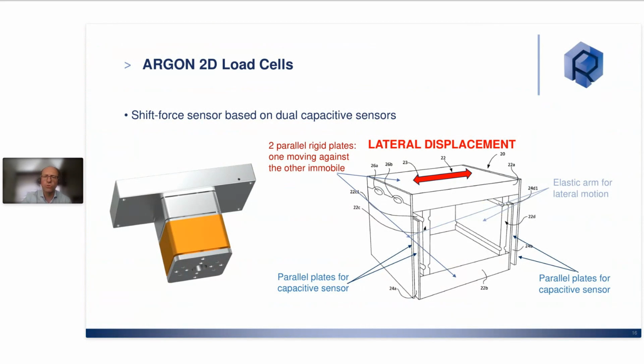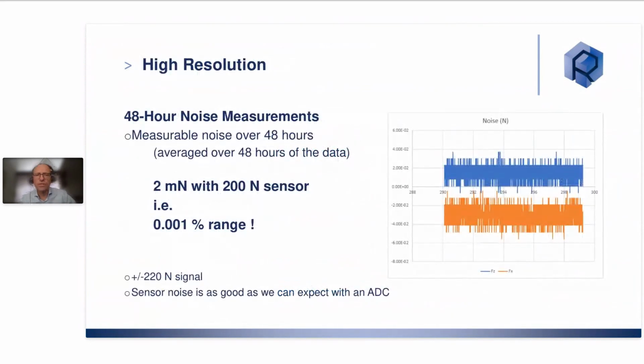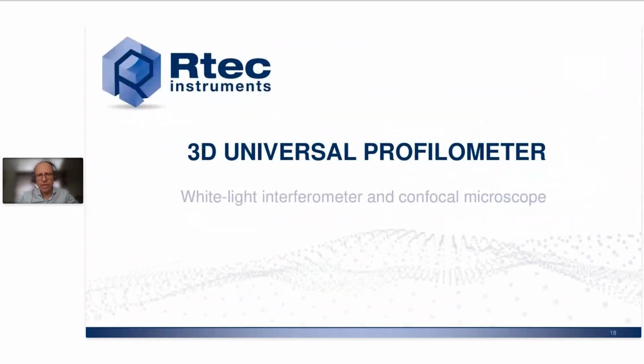And the fact that you have two sensors is making high stability measurements and high precision measurements. And this is really a high technology that we can explain to you more in detail if you are interested, but that really brings a lot of stability, meaning that we can do measurements with this capacitive sensor over a 48 hours time. And we are in fact showing a very high stability and no thermal drift with this kind of instrumentation.